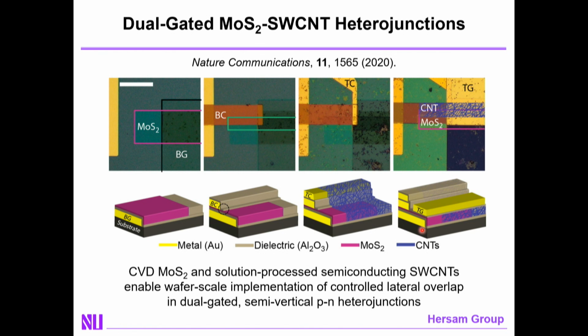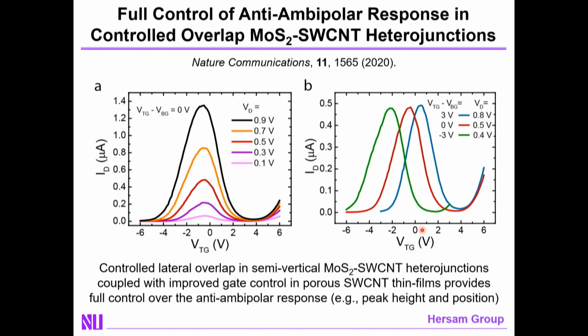The net effect of which is that you can achieve exquisite tunability over the resulting current voltage response. Particularly, what you observe, if you look at the current through the device as a function of one of the gate voltages, in this case the top gate, is that the device is off at high negative voltage because you fully depleted the N side of the junction. It's off at high positive voltage, you fully depleted the P side of the junction. Only at low gate voltage is the device on. And as a result, you get this Gaussian response, also referred to as an anti-ambipolar response, because it's a flipped over version of an ambipolar transfer curve.